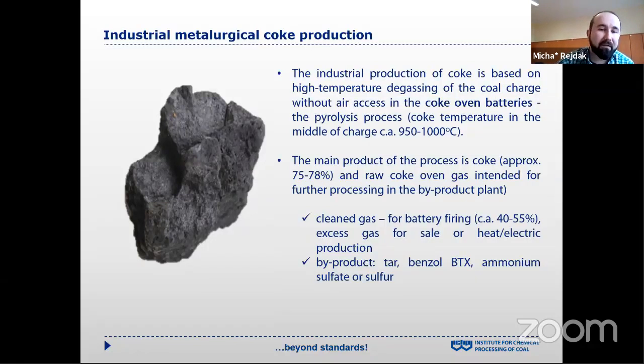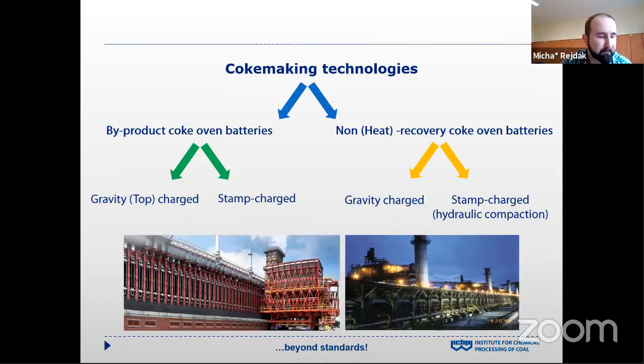The main product of the process is coke, approximately between 75 and 78%, and raw coke oven gas, which is intended for further processing in a byproduct plant to obtain cleaned gas. Between 40 and 55% of the cleaned gas is used for battery heating, and the excess gas can be sold or used for electricity production. And apart from coke, we have byproducts like tar, benzol, which contains benzene, toluene, or xylene, ammonium sulfate, or sulfur.